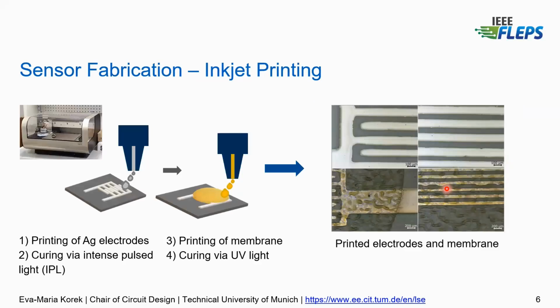Now I will compare two manufacturing methods of our sensors that we investigated. The first one is printing of the sensor. We used inkjet printing, and we printed the silver electrodes first. Then we cured them to make them conductive using intense pulsed light, because our PET foil was very temperature dependent, so we couldn't heat the substrate. Then we printed the ion selective membrane on top and cured it via UV light.